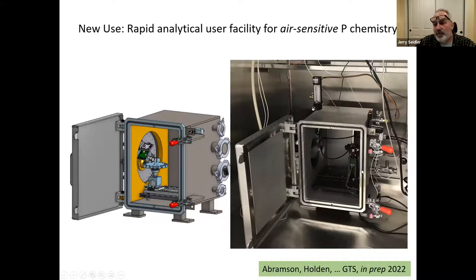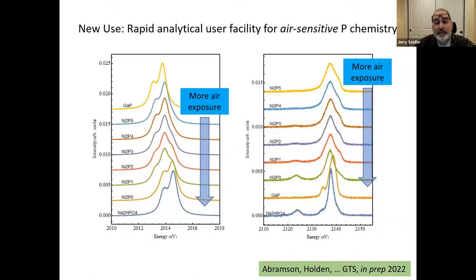The helium box, which could be a vacuum chamber, but we run it in helium, is also thick enough to serve as the radiation enclosure. And the data is wonderful. Here is phosphorus K alpha for reference compound gallium phosphide, which is reduced, and the phosphate, which of course is oxidized, and the sequence of samples, which are all nickel 2 phosphide, but with different, the 0, 1, 2, 3, 4, 5 is referring to, in inverse order,